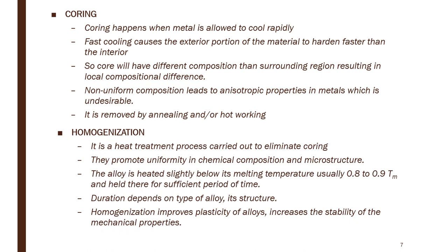Homogenization is a heat treatment process carried out to eliminate coring or dendritic segregation in a cast structure in order to promote uniformity of chemical composition and microstructure. The alloy is heated slightly below its melting temperature, usually 0.8 to 0.9 of the melting point, TM, and held for a sufficient period of time for solid state diffusion to take place. It results in a uniform composition throughout the alloy. The duration may vary from 1 hour to several hours, depending on the type of alloy, its structure, and the degree of inhomogeneity.